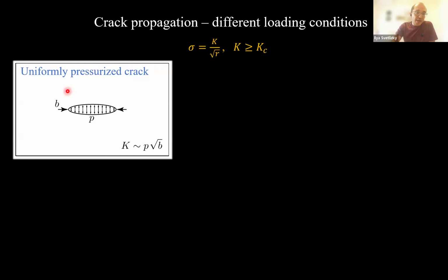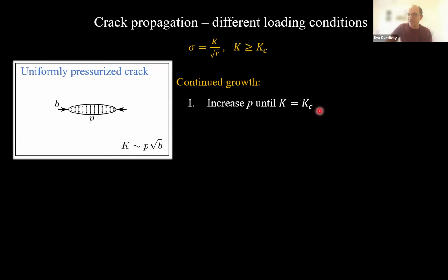For example, if you imagine a uniformly pressurized crack with initial length B, the stress intensity factor will be proportional to the pressure you apply, and it will increase like the square root of the length of your crack. So you start with some seed crack with initial length B, you increase the pressure, the stress intensity factor grows, it reaches the critical value, and the crack starts propagating. As the crack grows, K increases, so you have an excess of elastic energy, and all this excess, K larger than Kc, goes to acceleration of the crack.